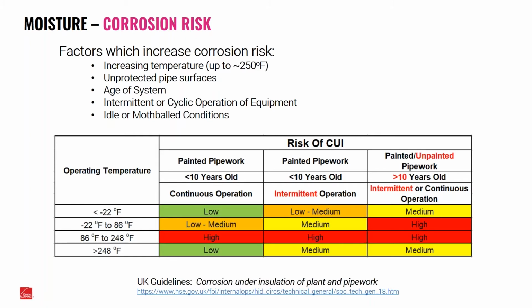And then, as you get to older equipment, things like that, you can see our risk is now from medium to high. So really, the takeaway from this is if we're going to be in that 86 to 248 degree range, we have to make sure that we keep that system dry, because we just don't have enough energy to get rid of that moisture that's in the system. Particularly if we have an older system, we want to be mindful of that. And if possible, if we're going to be in that range, we really want to consider using a coating to help protect against corrosion, to at least help mitigate that problem.